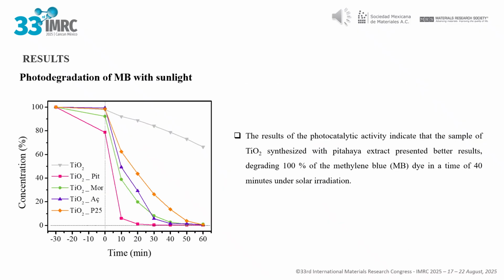Results. The results of the photocatalytic activity indicate that the sample of TiO2 synthesized with pitahaya extract presented better results, degrading 100% of the methylene blue, MB, dye in a time of 40 minutes under solar irradiation.